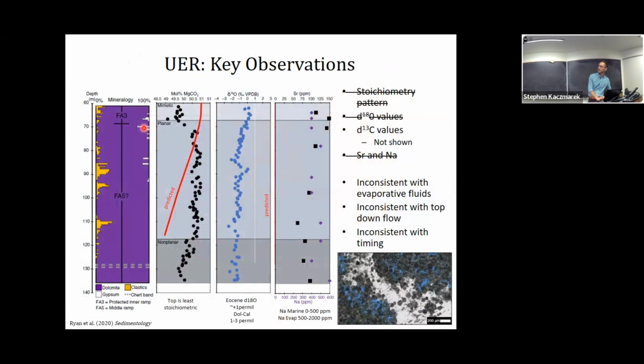So here is just a mineralogy section. Essentially it's all dolomitized, so we can't use the abundance of dolomite to say much. The stoichiometry of the dolomite at the top is around 49.5, and then it actually increases through the middle of the section and then decreases. This is not really consistent with our predicted value of being highest near the top where those fluids were coming from and decreasing downward.